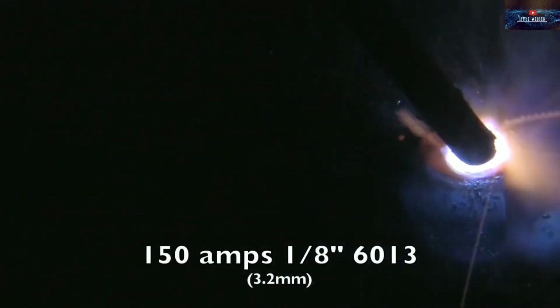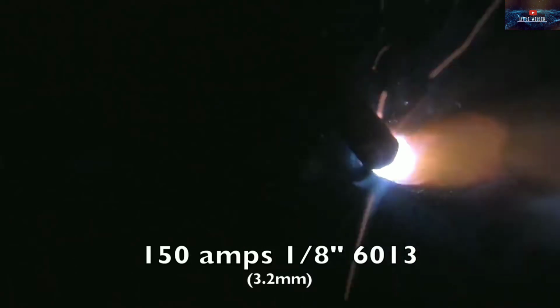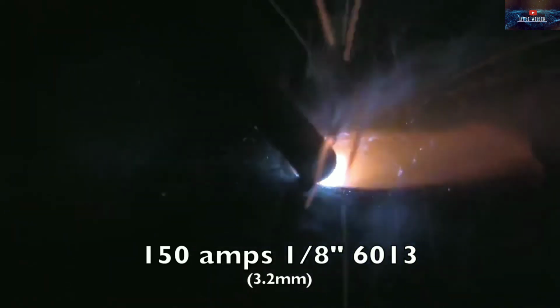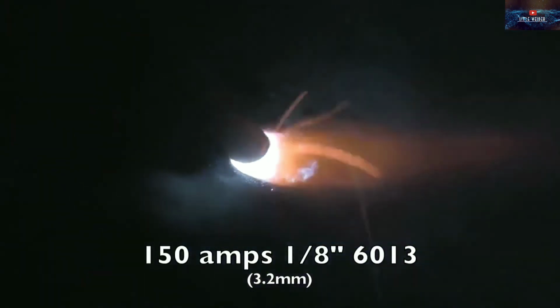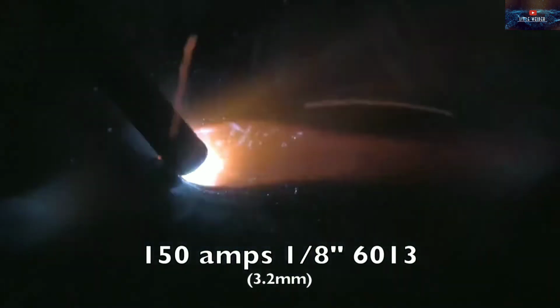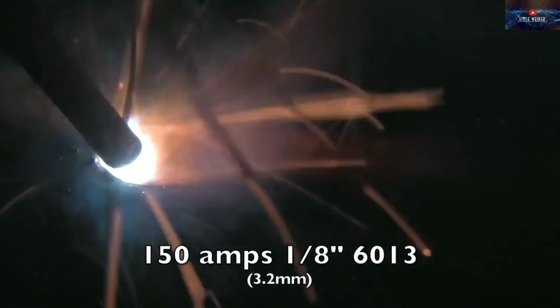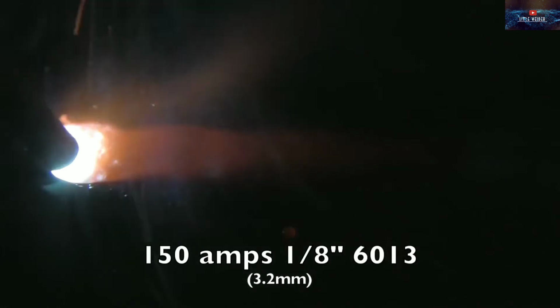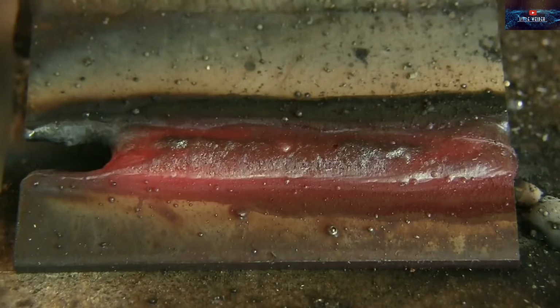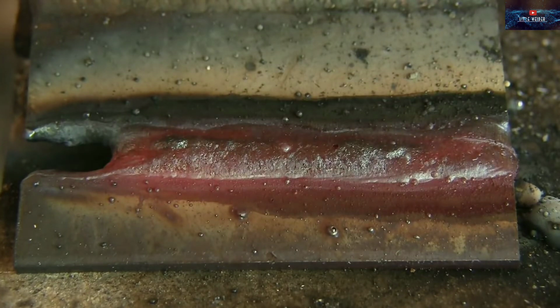Amperage too high. This is especially a problem if you're welding out of position or on something a little thin. Now I have switched to a little bit thinner metal here just to exaggerate it. You see how far the puddle is hanging back behind the arc. It's a really super long elongated puddle, and here at the end, boom, blows right out. Using too much amperage, you can't control it.